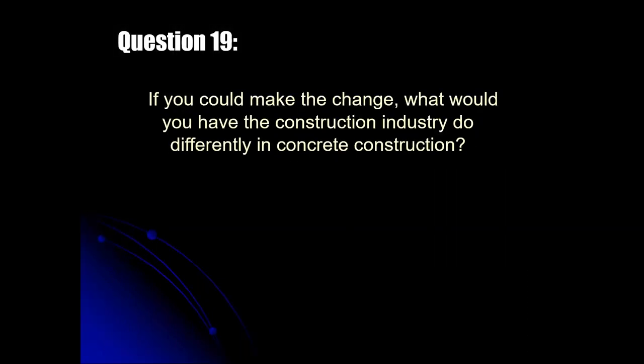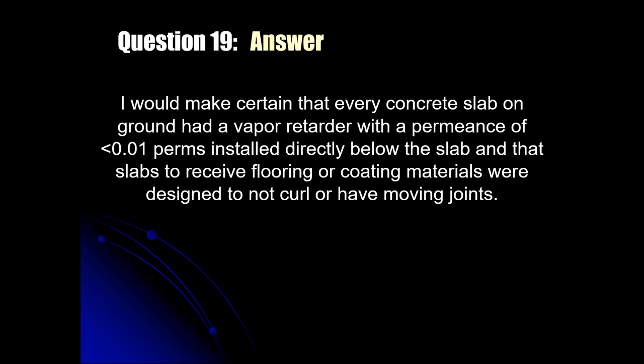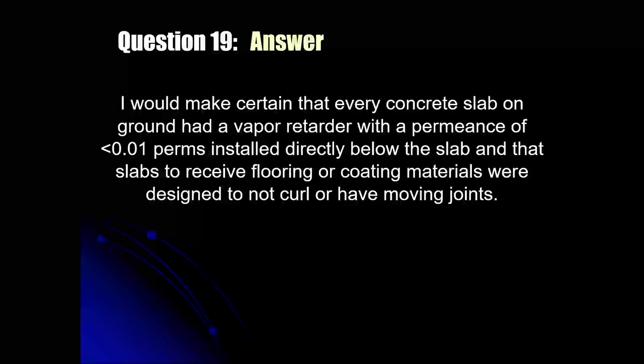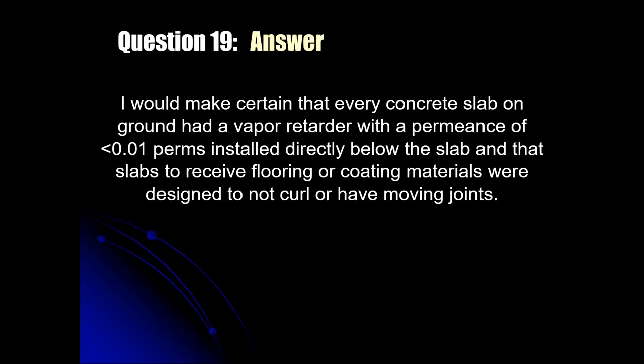If I could make the change, what would you have the construction industry do differently in concrete construction? First of all, I'd make sure that every concrete slab on ground had a low permeance vapor retarder with a permeance of less than 0.01 perms. And I would make sure that number is achieved not only before, but after that material is put through the performance requirements of ASTM E1745, which basically replicate what's going to happen to that material when it's in the ground over a prolonged period of time. There are a lot of materials that look pretty good until you subject them to those tests, and then their values drop off significantly.